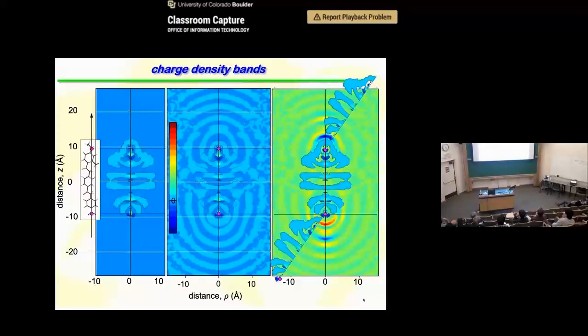Okay, so we looked at this in detail in the atomistic simulations. So here's the molecule. We pick a molecule, and we assign it a coordinate system where the z-axis is along the line that connects the 2 ends. The origin is around here. We then calculate the charge density of the chosen molecule and of all the other molecules and average over the ensemble. So these plots show the conditional charge density of the chosen molecule, and then the conditional charge density of all the other molecules out here, and then the chosen molecule in the middle here.